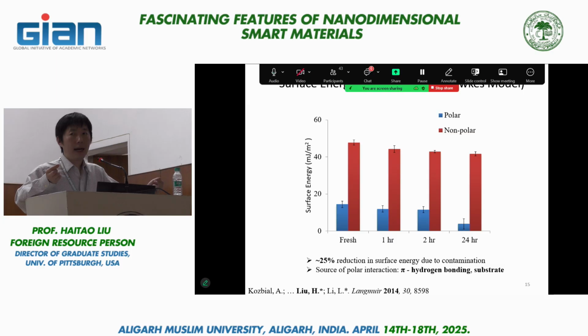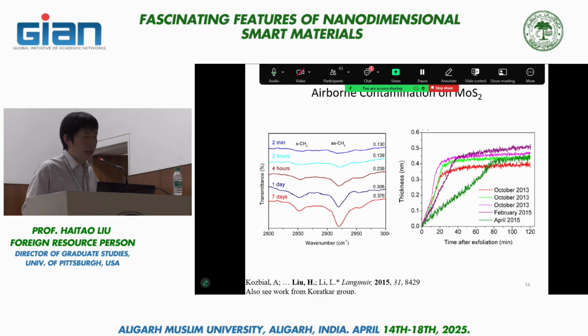Now, the slope of this growth, which is the kinetics, actually differs quite a bit depending on when we do the experiment. In this paper, we spent almost 2 years collecting different kinds of data, and this turned out to be sensitive to the environment as well. Which is not entirely surprising, because the environment can produce a lot of hydrocarbon depending on whether it's spring, with a lot of flowers in Pittsburgh, or in the winter, when everything's dry, and so on and so forth.